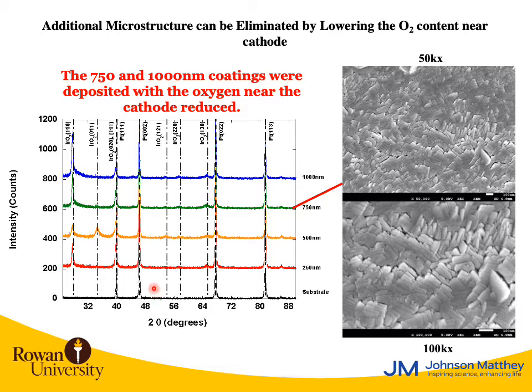As we continue the depositions, so here is the 250 nanometer coating made at 200 degrees C, and you don't see that 011 peak. At 500 nanometers you see it, and then what we've done here to suppress it at 750 and 1000 nanometers is we've lowered the oxygen partial pressure, and we saw that we could suppress that formation. And so when the coatings get thicker, and at 250 you see these sort of larger grains and more organized grains than what we're seeing in the low temperature deposition.